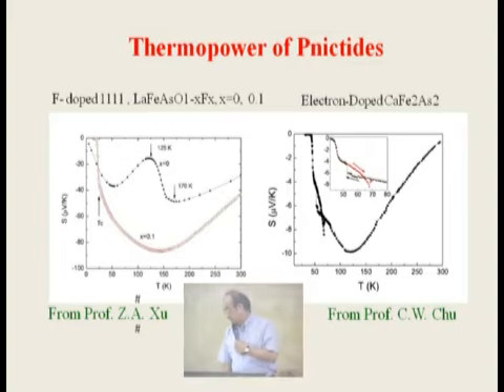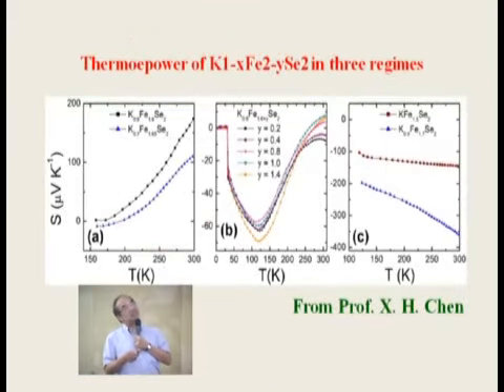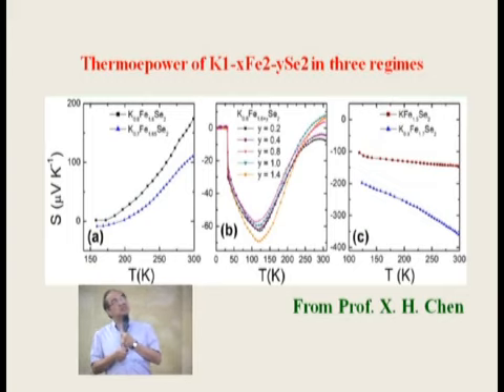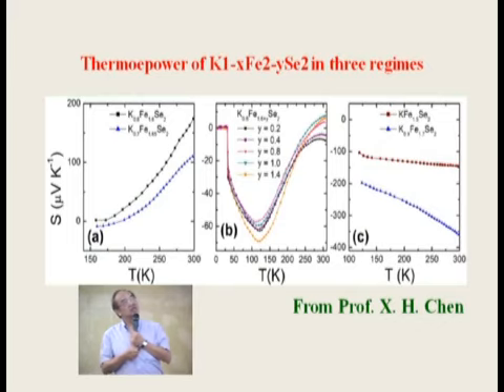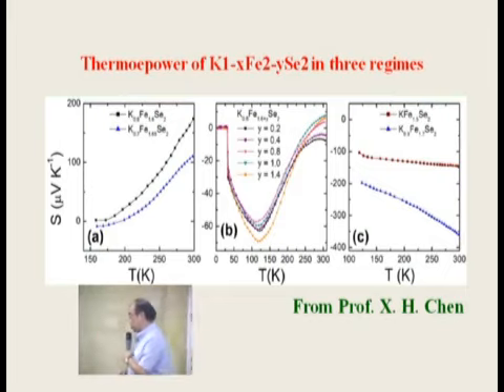Okay. And in fact, more recently, there is a new discovery following our 1111 system. A Chinese group also managed to make a 1-2-2 with selenium instead of arsenic. And that also becomes superconducting. And the data also strongly show that only the samples which are superconducting show this kind of thermal power behavior. For non-superconducting ones, because you can change the composition and they become non-superconducting, that feature disappears. So this maximum thermal power seems to be a very important feature. Okay, and what is this feature?